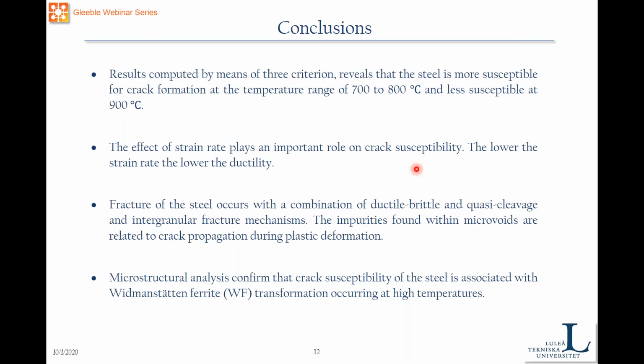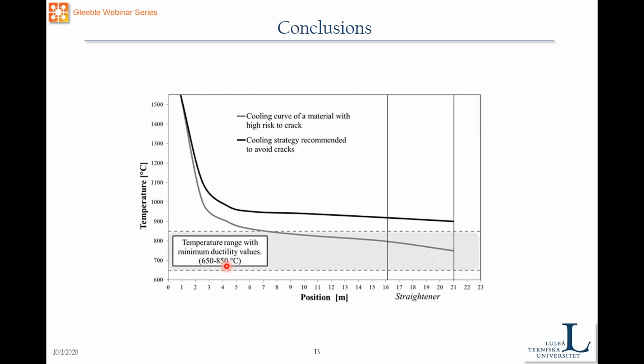The fracture of the steel occurs with a combination of ductile, brittle, quasi-cleavage and intergranular fracture mechanisms. This can also be promoted by the formation of impurities, microvoids, or by plastic deformation. Microstructural analysis also confirmed that the crack susceptibility of the steel is associated directly with the Widmanstatten ferrite transformation occurring at high temperatures. One of the conclusions that could help the company is that by avoiding this ductility range, or low ductility zone, as I call it, it is possible to avoid the formation of transverse cracks in the material.